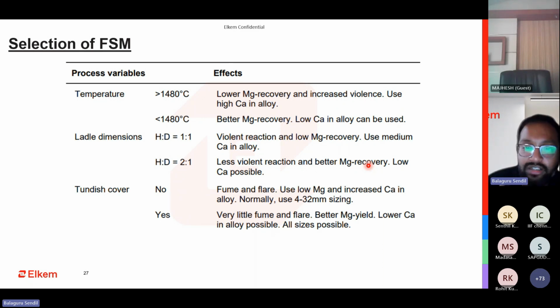There are a lot of ladle suppliers who are supplying with a quick change mechanism. It doesn't take more than 30-40 seconds to remove the tundish. So it is no longer the case that it's going to take 1.5 minutes, eat up my tapping time and eat up my cycle time, so that I have to increase my tapping temperature. A lot of people have developed very nice ladles in India where you are able to remove the tundish cover within less than 60-70 seconds. So that is a very nice option you should always have, to go for a tundish ladle.